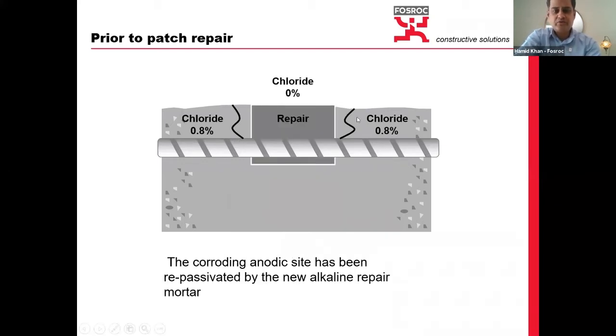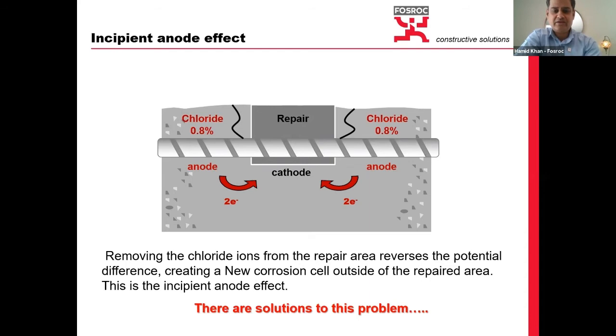So what happened? We removed that 4% chloride area and we made it 0% chloride. So what happened now? The potential still exists. The difference between the two areas still exists. The only thing we have done is reverse the areas, as the repaired area is now called cathode and the area adjacent to it is now called anode. Now the corrosion process would start again and the areas adjacent to it would start deteriorating. So removing the chloride ions from the repair area reverses the potential difference, creating a new corrosion cell outside of that repaired area.